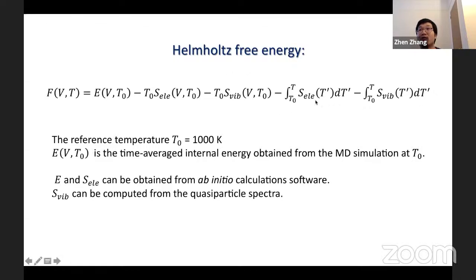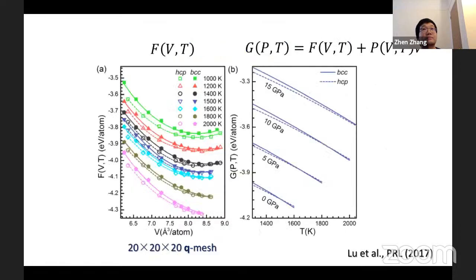the electronic contribution to the entropy should also be integrated for metallic beryllium. So both E and S electron can be obtained from ab initio calculation software, while the S vibrational was computed from the quasi-particle spectrum. Vibrational entropy was computed with a dense converged 20 by 20 by 20 Q mesh, and Helmholtz free energy was obtained. F as a function of Vt for both phases are shown here on the left.